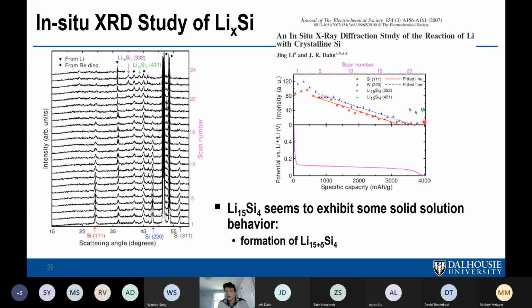The other thing is this phase hangs around and you can put more lithium in. And all publications about this phase say it has some solubility for lithium. You can put some extra lithium in here. I don't know if that's true or not, because I don't think there's any room for any more lithium in lithium 15 silicon 4. I tend to think that you first form a phase with some vacancies, and then maybe you can lithiate further and make the 15-4 phase, because really there isn't more room for anything in the 15-4 phase. So I kind of find that hard to believe. But at any rate, there's some composition variation in this phase.